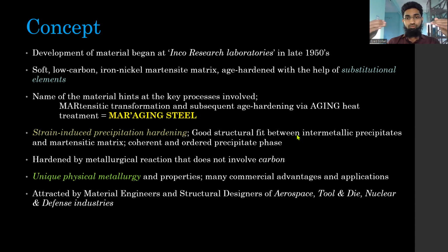And this was very readily heat treatable. A simple heat treatment cycle was another advantage that it presented as a unique factor to the industry. So you have an outstandingly tough martensite, strengthened rapidly to extraordinarily high levels. The strength achieved is rapid, it doesn't take many heat treatment cycles or a complicated heat treatment cycle. And this is a concise and objective way of looking at the strength it achieves.